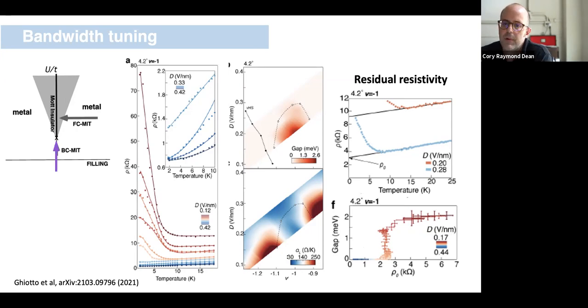There are some indications in some theory work that this abrupt change in the residual resistivity is something you might expect. And you might be able to correlate that with the existence of some superfluid transition, not superfluid, sorry, a spin liquid transition in the system. So I'm not asserting that, I'm just asserting that in the data we see this kind of abrupt change, and that may or may not indicate something interesting.